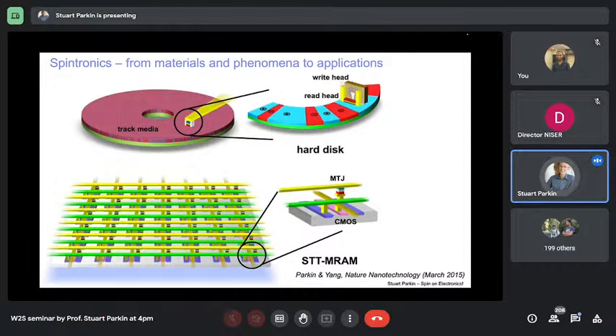In those cases, the magnetic fields required to change the orientation of the iron layers, let's say in a superlattice, were very large. They're of the order of 2 Tesla. Here, we need fields of just a fraction of an Ørsted to reorient those magnetic layers. So this spin valve then is a very interesting device. It can detect tiny magnetic fields.